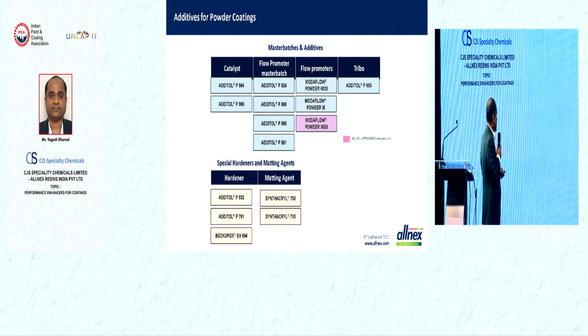And from the hardener side, again we have a wide range. This Additol P932, P791. P932 is a urethane pre-polymer, recommended for polyurethane powder coating. Then Beckopox EH694 is an aromatic polyanhydride hardener. P791 is an aliphatic polyanhydride hardener to be used in powder coating applications. And Syntacryl 700, 710 are matting agent hardeners. These are glycidyl functional acrylics used as matting hardeners.